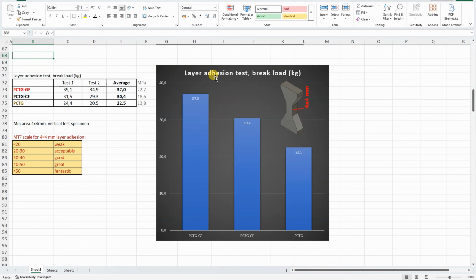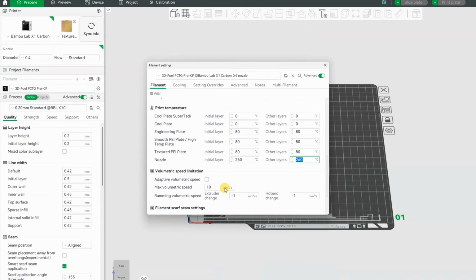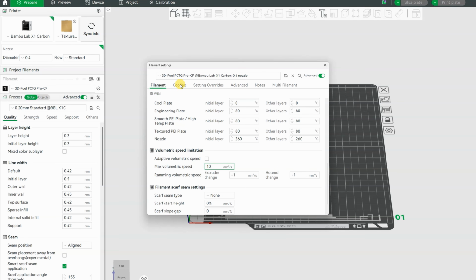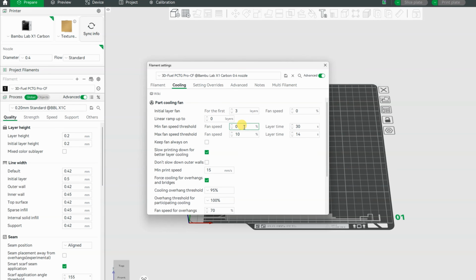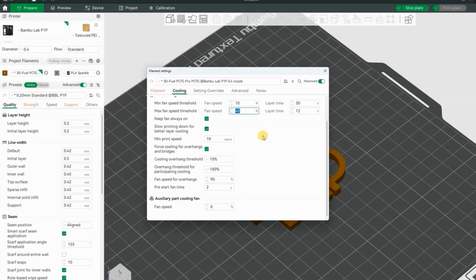This was a very pleasant surprise because usually fibers make the cross-section weaker, but it looks like this fiber sticks well somehow to the base material, because this is good layer adhesion according to my rating and stronger compared to the no fiber PCTG. One of the reasons for better layer adhesion of fiber versions is smaller part cooling, only between 0 and 10%, while with the PCTG it was between 10 and 40%.